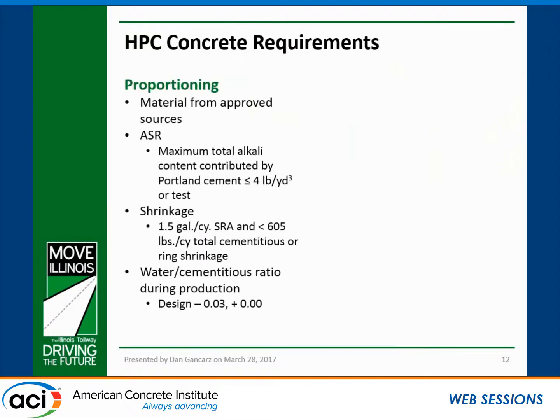So our spec requirements, we have some proportioning requirements. So all materials have to be from an approved source. This is either primarily IDOT, the Illinois DOT approved materials, or for special materials, the Tollway has approved lists. We evaluate ASR at the proportioning stage. We limit the alkali loading from the Portland cement to less than 4 pounds. If the producer would like to go over that, we allow that, provided they perform ASR testing.